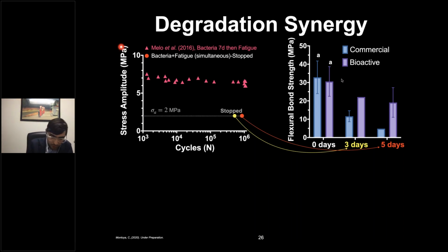Here I'm showing you a typical fatigue curve, with stress amplitude and cycles. Think of the x-axis as time and the y-axis as stress. This is what we found back in 2016: if you apply a stress of 5 megapascals, you can say your composite has an infinite life—you can keep applying that force and it will never break.